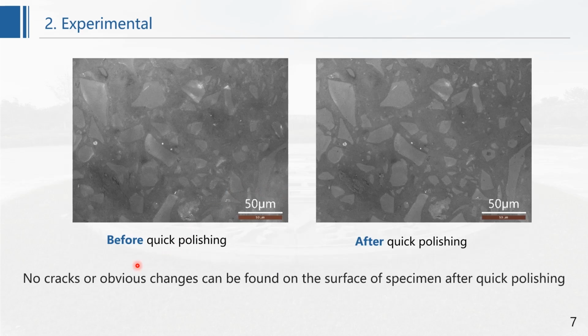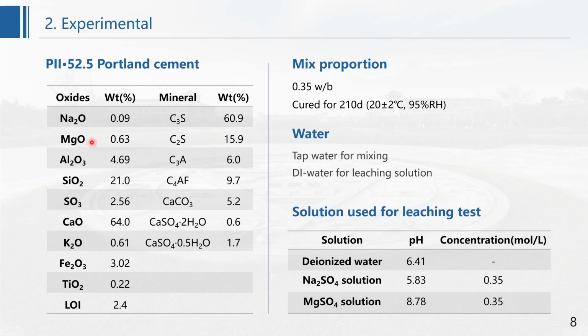Here are the optical images of the surface of the sample before and after the quick polishing process. According to the images, we can see that no cracks or obvious changes can be found on the surface of the sample after quick polishing, which suggests that the quick polishing process has little effect on the surface of the sample.